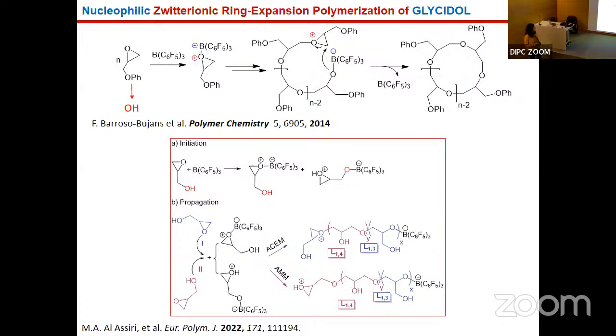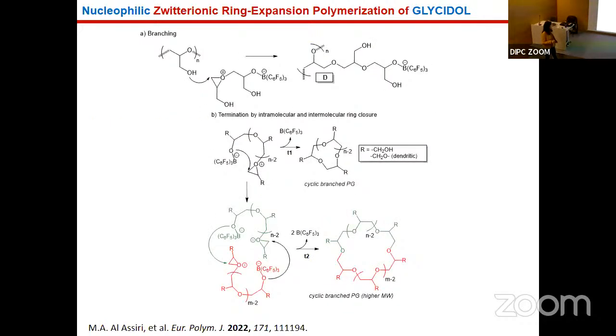Why? Because the catalyst is able to react through the oxygen of the epoxide group, but also through the hydroxyl group. And then the polymer structure is more heterogeneous in the sense that there are more types of structures here, but also branching reactions. This hydroxyl group can react with the growing chain and can form branches. The cyclic polymers are formed, as we identified by MALDI, but we also observe different features in the polymerization. It is also possible that ring fusion of two chains could happen, which would explain the increase of the molecular weight of these systems.